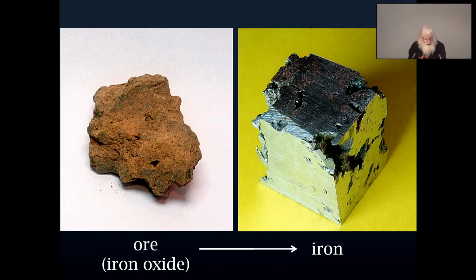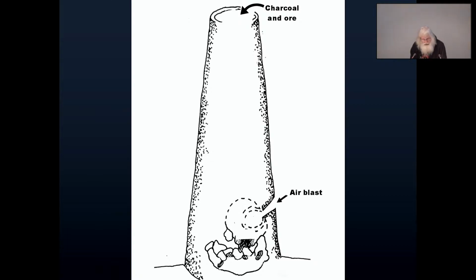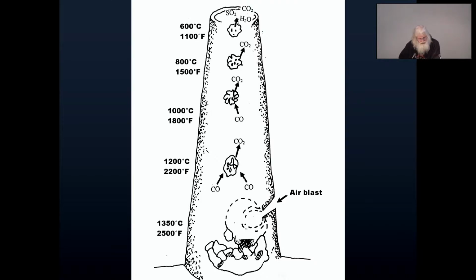And it's done inside an oven. And in the oven, a complex set of conditions are created. And these conditions rip the oxygen off of the iron ore to leave us with pure iron. And the way this is done is that charcoal is burned, and it creates very high temperatures in the oven. But importantly, it creates an atmosphere of carbon monoxide, and the carbon monoxide wants to rip away these oxygen atoms from the ore. Now, it's a complex process. There's many different chemical reactions taking place at different parts of the oven.